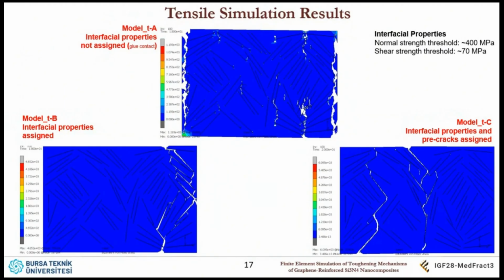And so subclasses of tensile models. TA, so tensile A, tensile B, tensile C. 3 basic models. Tensile A doesn't incorporate any interfacial properties. Okay, it just assumes graphene is firmly connected to the matrix. And second model, TB, tensile B, incorporates interfacial properties. Normal strength threshold is about 400 megapascals. Shear strength threshold is 70 megapascals. In the third model, in addition to these, I applied pre-cracks in the interfaces.